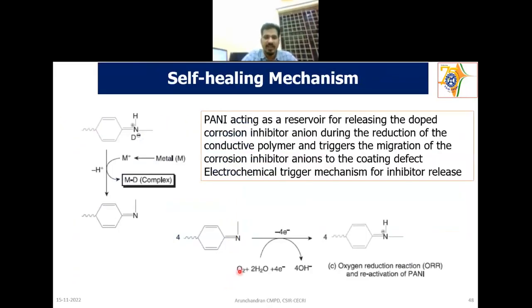Then another one is a self-healing mechanism. Pani acting as a reservoir for releasing the doped corrosion inhibitor. So when the Pani undergoes reduction, the doped anion gets released, and the metal cation will make a complex with the doped anion, and the metal cation-anion complex will form on the surface. So this is another mechanism, that is the self-healing mechanism for the corrosion protection. And this is another one, a cathodic protection one. We'll come to that in the next slide actually.